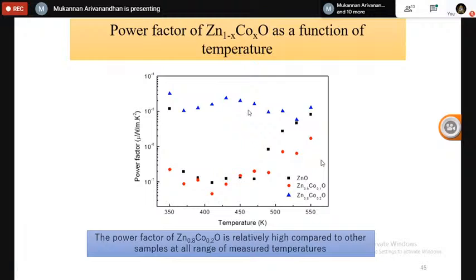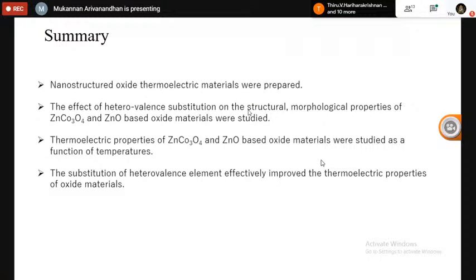So this shows that by properly choosing the dopant with a different valence state, one can tune the electrical characteristics of the material. Thereby, one can enhance the thermoelectric performance of the oxide-based thermoelectric materials. Okay, so this is my summary. We have prepared a lot of thermoelectric materials, especially oxide-based and semiconductor-based thermoelectric materials. In this particular topic, I've shown some of the results on zinc cobalt oxide and zinc oxide, and systematically varied the heterovalence dopant in the system, and the substitution of dopant effectively modified the thermoelectric characteristics.